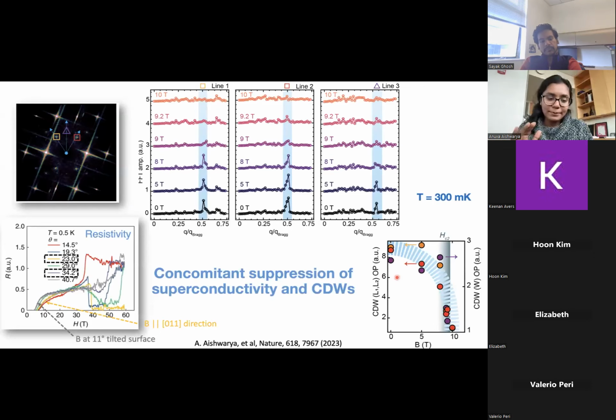tilt on the sample, which means, so 23-degree is our actual direction because of this cleave plane, and if you add 11 to that, it's 34, and along that direction, the critical field is much smaller, which means that we can actually reach the critical field, and that's why we're seeing this suppression of the CDW. So what this means is that the CDW is killed as superconductivity is killed in this material.